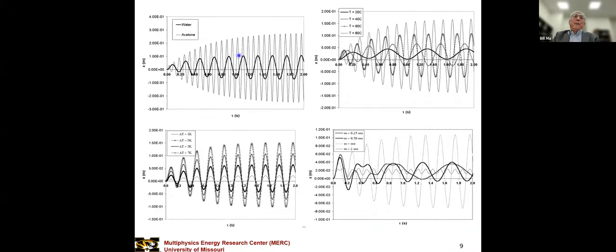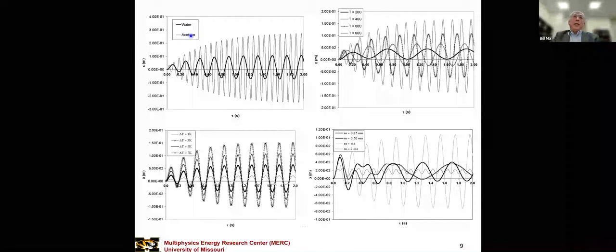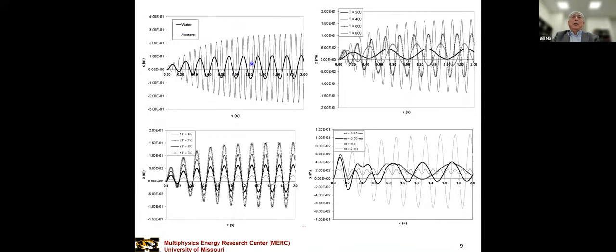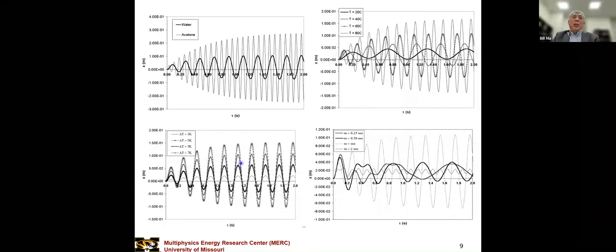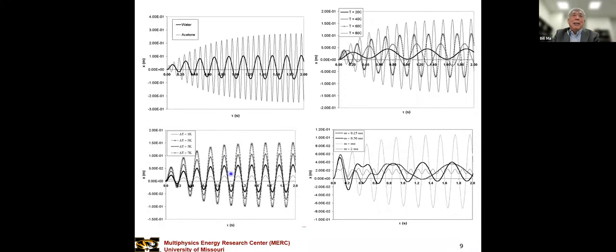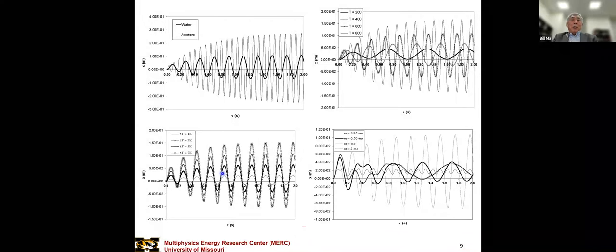This result shows that acetone can produce stronger oscillating motion. That's very similar to the experiment data. And this figure shows that when the operating temperature goes up, the oscillating motion is stronger. That's also similar to our experiment result. When the temperature difference between evaporator and condenser goes up, the oscillating motion is stronger. That also has the same trend as the experiment data.